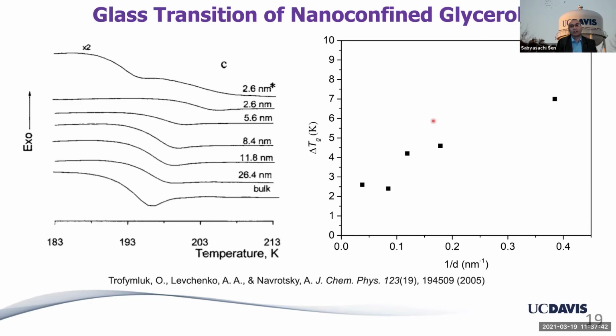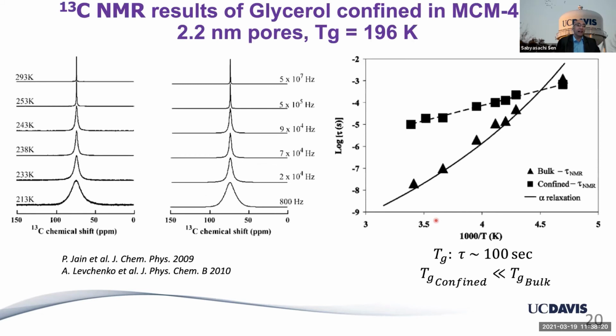So first of all, a word on confinement, again going back to one of the early works by Alex Navrotsky's group, that this is the glass transition of nano-confined glycerol, where you can see the glass transition temperature changes. It actually increases with decreasing pore size. So this is the inverse of the pore size. And this is a continuous behavior. So what is typical of glycerol then is an increase in TG with increasing confinement. Okay, please keep that in mind when we go to this next slide.